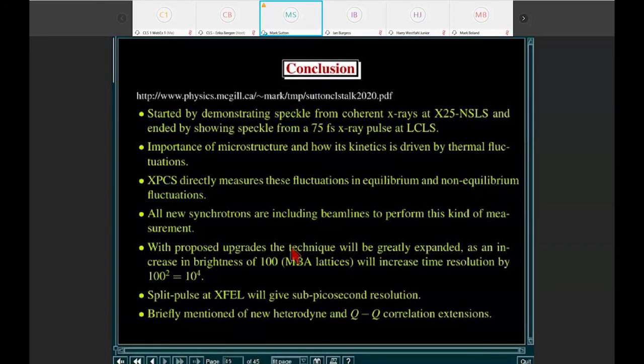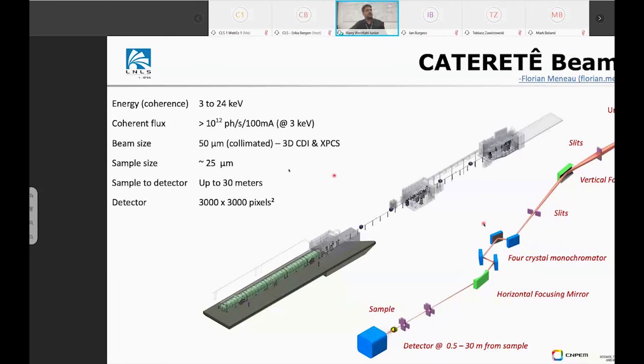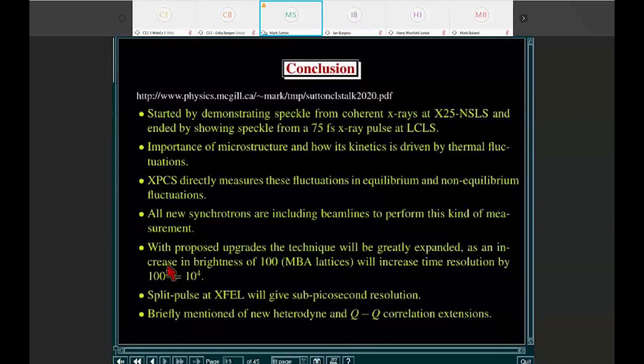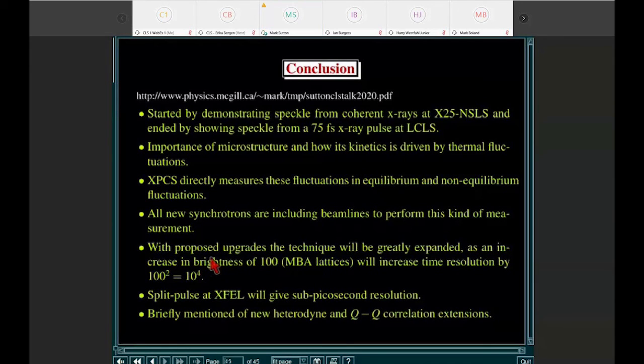For XPCS, because it's an intensity fluctuation measurement, basically the time constants that we can measure go like the square of the coherence. So with the new upgraded APS, we should be able to go 10 to the 4th times faster, assuming we could get the electronics and the detectors to work that fast. And that would be 1,000,000 times faster time constant at the CLS.